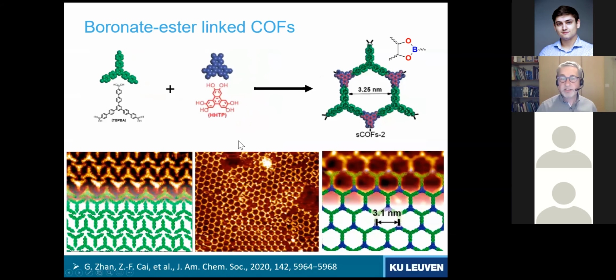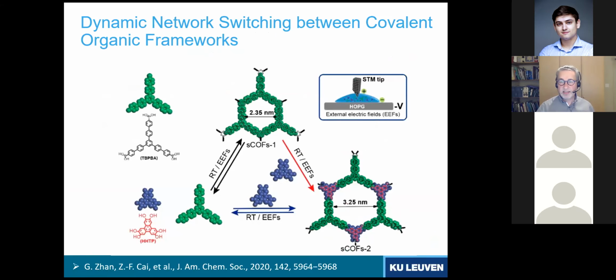That system is shown over here. Again, we use this boronic acid, but then we also add this molecule, and it's known that these two monomers can give rise to a different covalent organic framework, as shown here. These are images of the monomer. This unit, the HHTP, we cannot visualize by itself. But this is the monomer I introduced before, and this is after the polymerization. The interesting aspect of this approach was that by playing with the electric field, we could go from one stage to another stage.